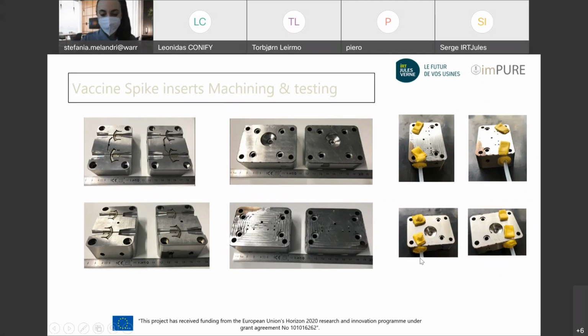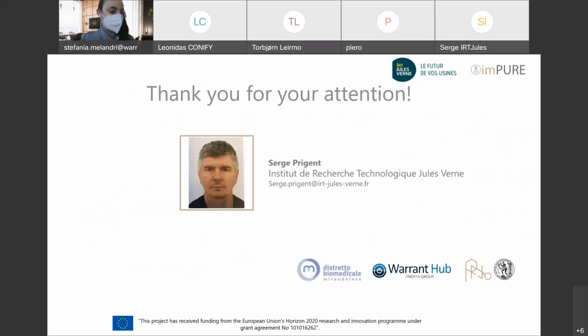And at the end, to make sure that the cavity was fully well manufactured, we have a leaking test, and we inject helium, and with the detector we found no leakage. That means that it was able to be set on the mold, on the master mold, and to have the first trial of injection. So if you have some questions, you are welcome, and you can reach my mail directly on the last slide.